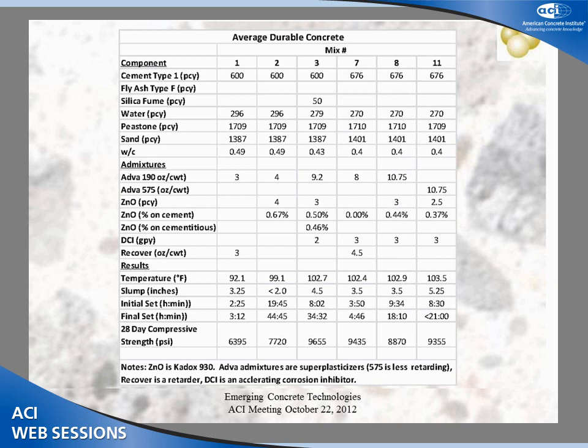As you can see here, if you look all the way at the bottom, at the compressive strength, the mix number 3 that had the Portland cement and the silica fume had significantly higher compressive strength. Comparing mix number 1 and mix number 2, they were both produced at the same water to cement ratio, 0.49. The mix that had the zinc oxide in it did have significantly higher strength at 28 days.